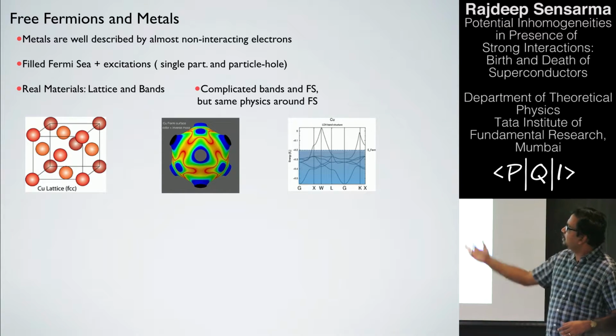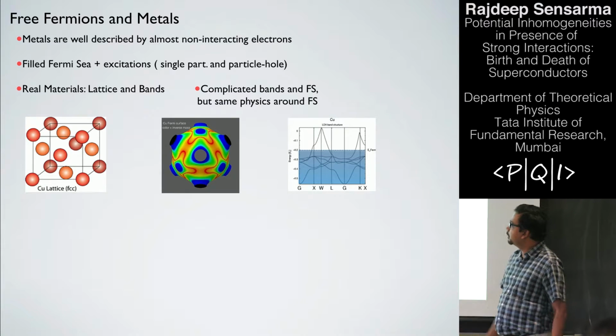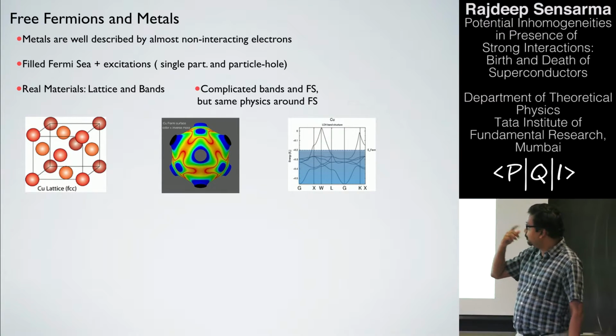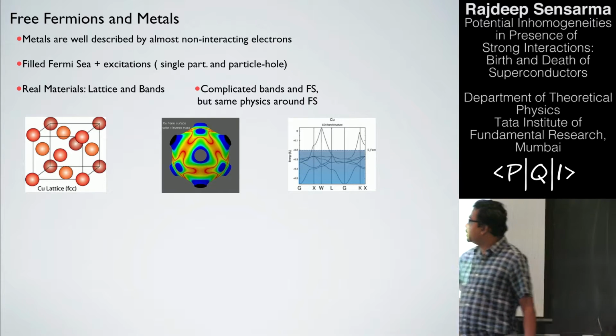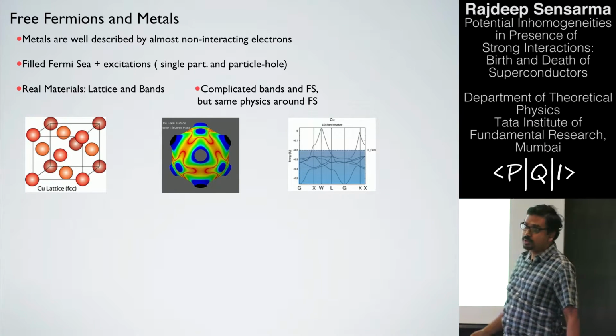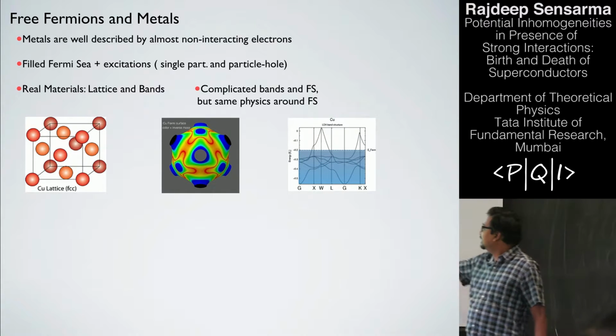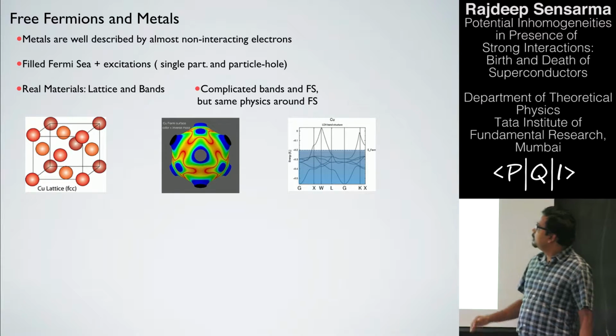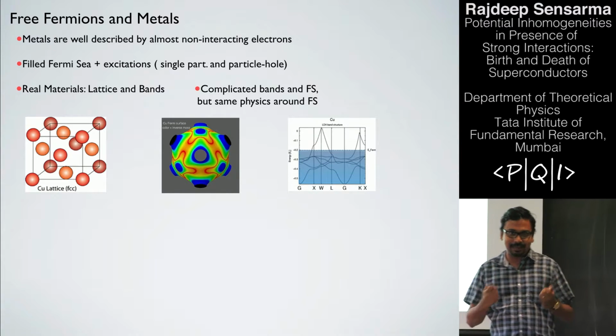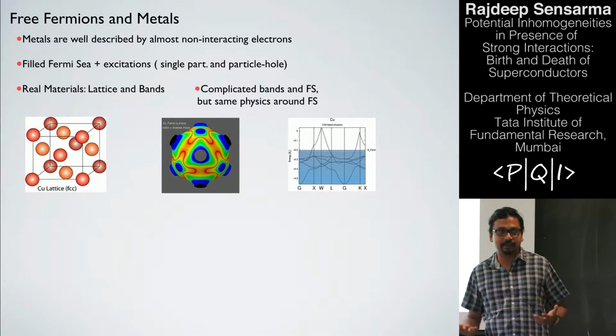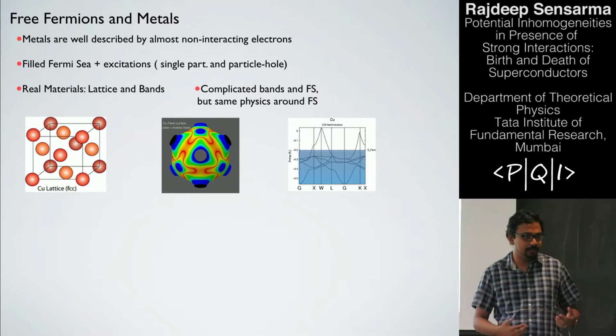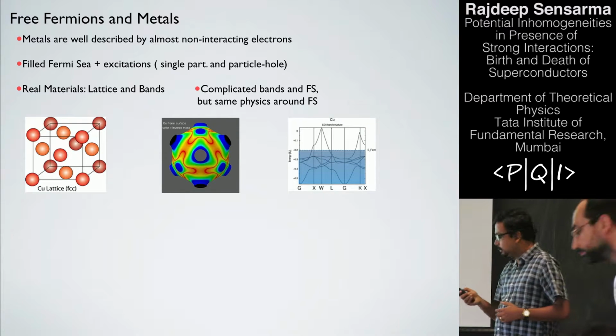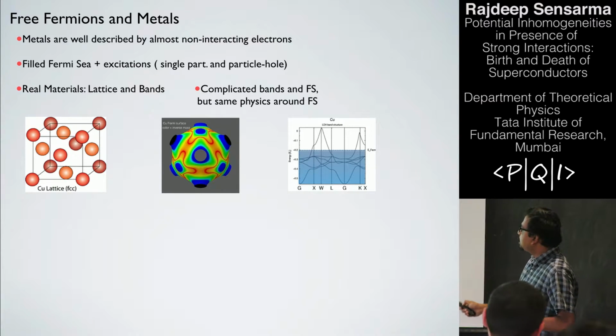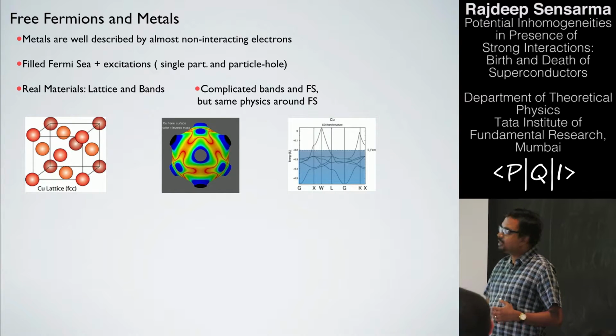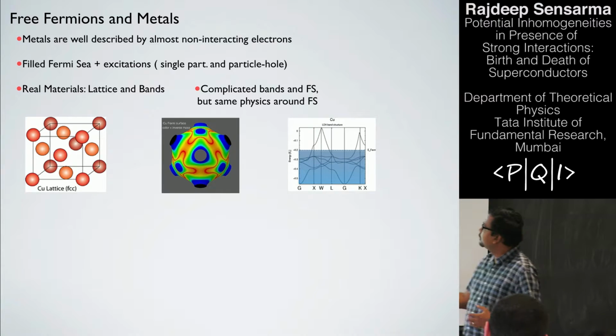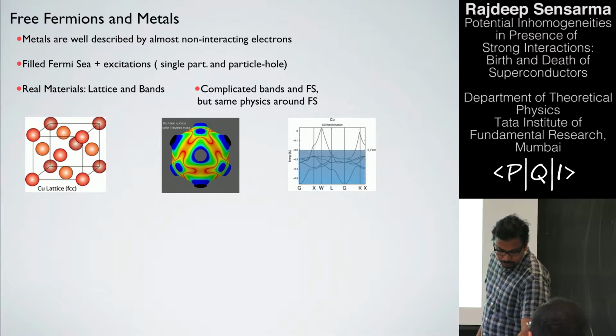Okay. Now if you have real materials, you have more complicated bands. This is just copper, which is an FCC lattice, and the Fermi surface might look that complicated. This is a picture of the Fermi surface in momentum space. This is how the band dispersion looks. So there's a lot of complication in getting the correct bands and so on. But once you have got them, it's still non-interacting physics. You fill it up to the Fermi level, and all the complication lies in finding where the Fermi surface is. But once you have that, it's basically the same physics around the Fermi surface that you get for free electrons.